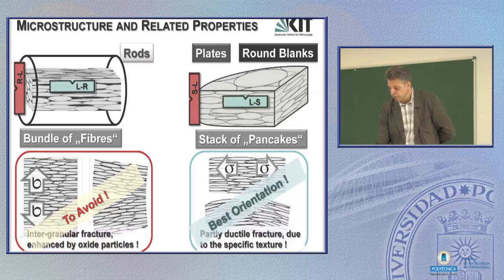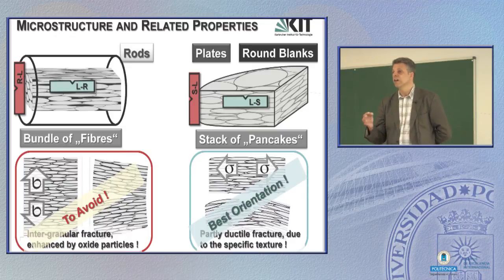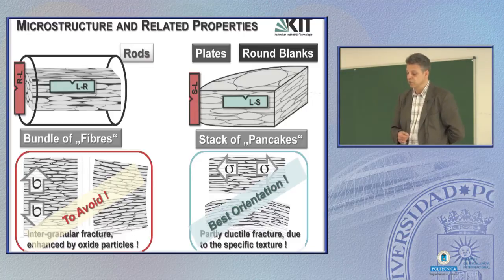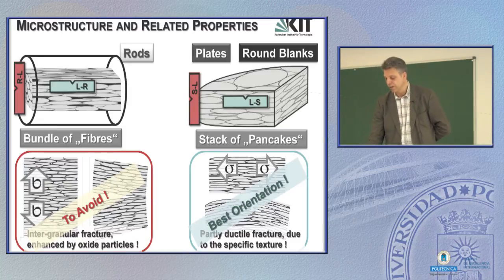That's not so good. On the other hand, if we load the material along the rolling direction, that's along the fibers or along the platelets or pancakes, then the material doesn't fracture so easily, because here the grain boundaries are much less. As a conclusion, you have to avoid this type of loading in a technical or structural application, and this is the best orientation in which you can load the material.